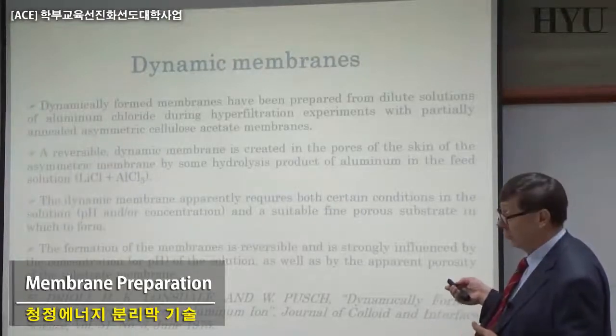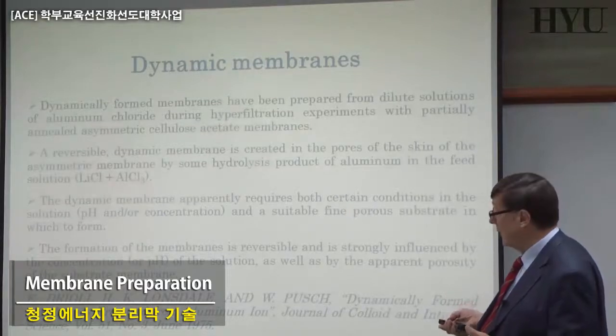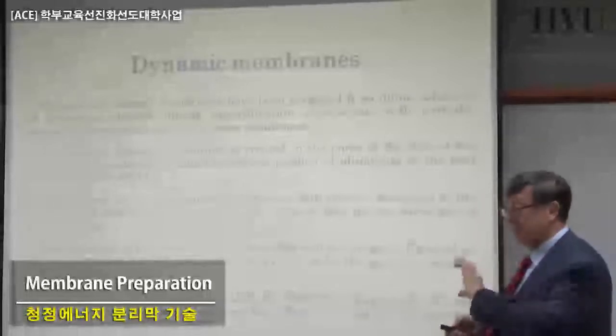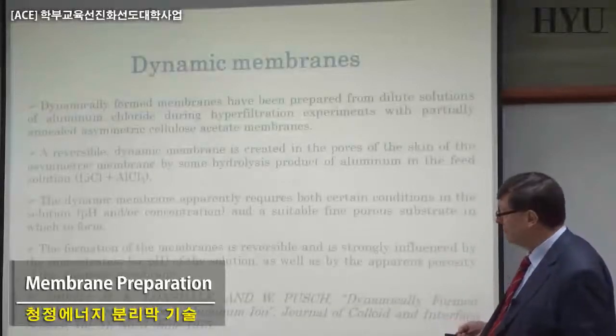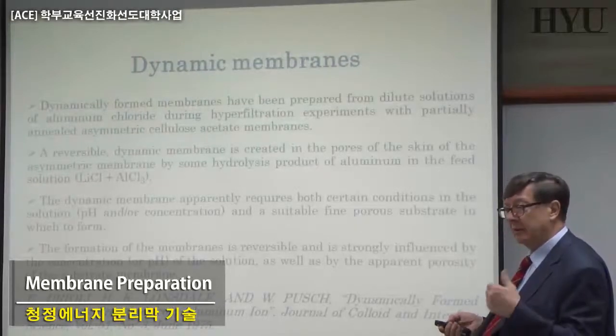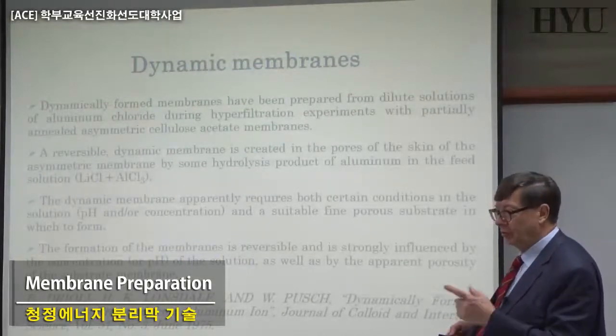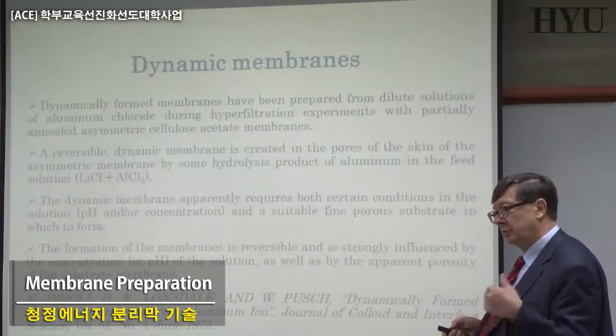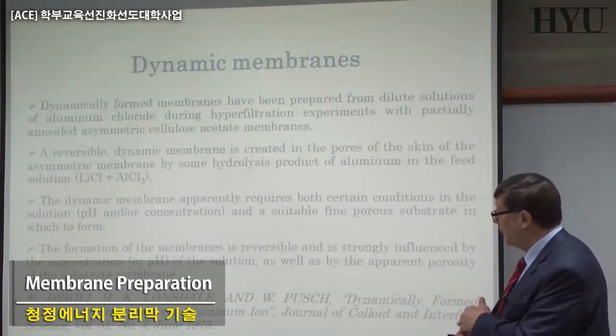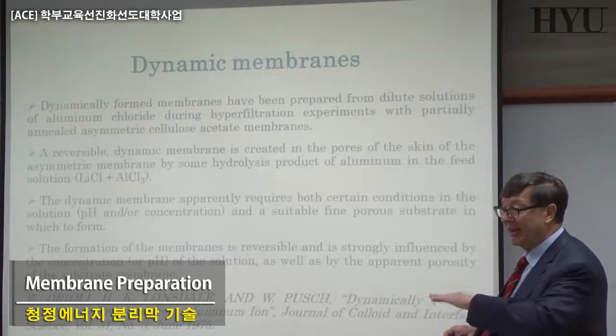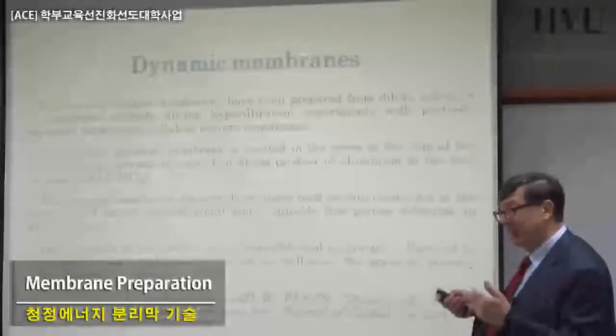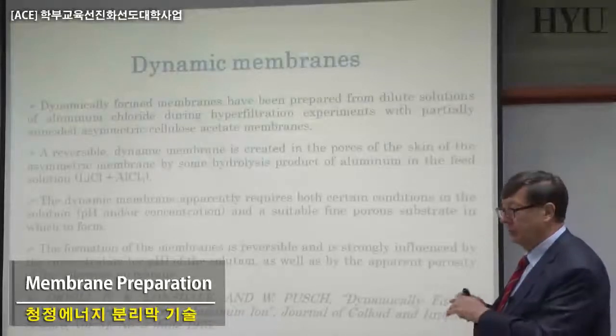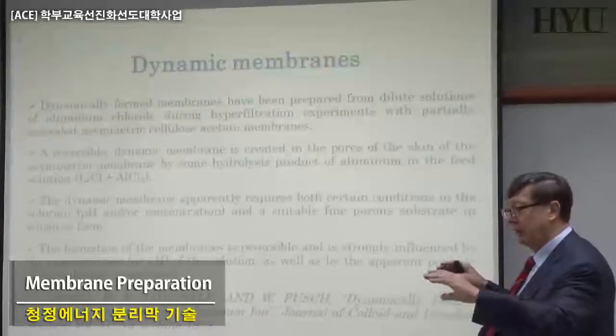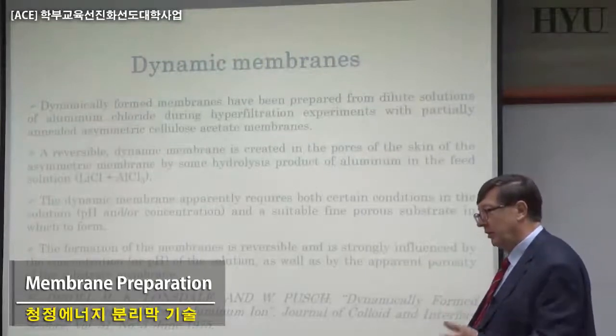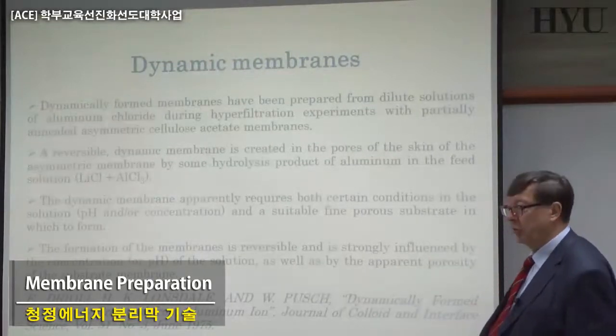And in nature, in industrial application, after this, people were producing, Union Carbide was producing on some microporous film a deposit of some chemicals, some hydroxide, alumina, iron, etc., to treat textile water. You can form first some dynamically formed gel layer, and these become selective and permeable to specific compounds. So Union Carbide, the big company, they were producing this nice module, and they were using this for the clarification, purification of the water from textile industry.